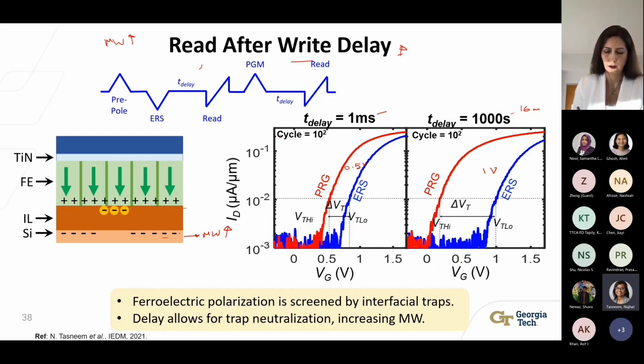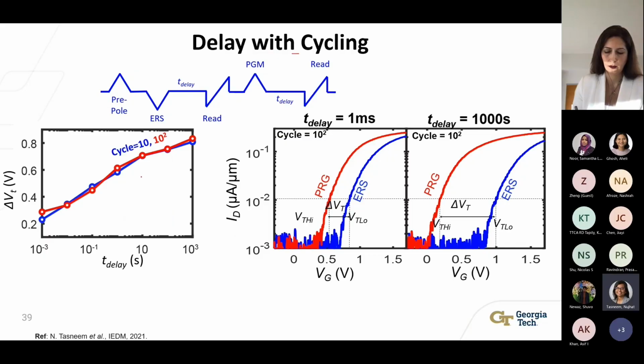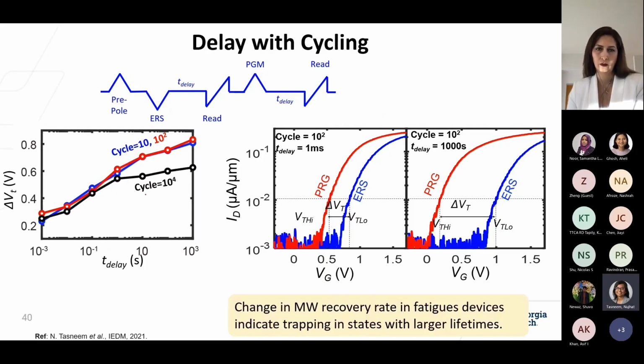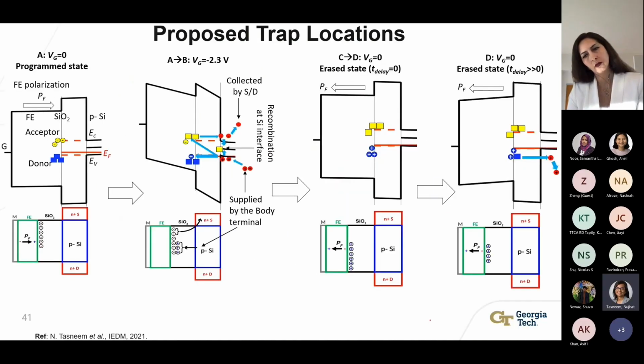So we tried to see how this read after write delay changes with fatigue cycling. This curve over here shows that up until 100 cycles, the rate at which the memory window increases with the read after write delay is almost constant. On the other hand, after 10^4 cycles, initially the memory window recovery rate is the same as before, but after around 1 second, this recovery rate significantly degrades. So again, this indicates that with cycling, fewer and fewer traps are being neutralized, which means that additional charges are getting trapped into states which have a longer lifetime, which means they are away from the interface and deeper in the band gap. So the results from this experiment helped us to paint a qualitative picture of trap location and dynamics in FeFETs with respect to the energy band diagram.